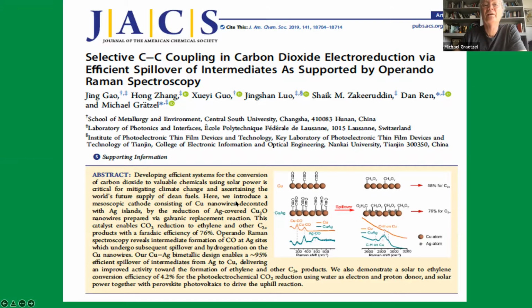And this still had an efficiency of between 4 and 5%, but we are now using flow electrodes that have much higher efficiencies. We got, for example, 20% efficiency for CO2 to CO conversion recently. So there's still a long way to go, but it looks very promising to tackle also the direct conversion of carbon dioxide, removing the greenhouse gas from the atmosphere and fixing it as ethylene, which itself becomes a feedstock for polymers. It will be stored in the form of a chemical.